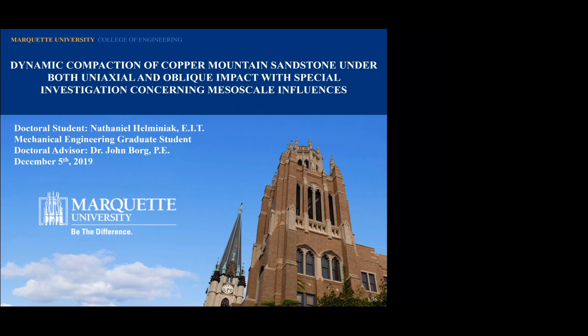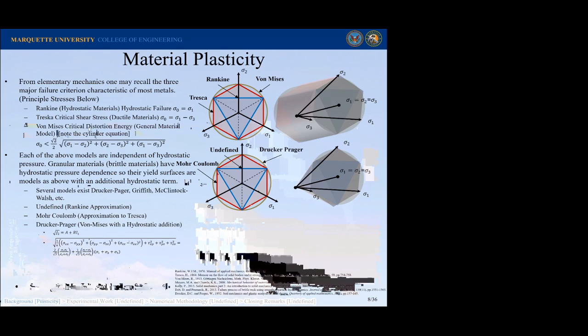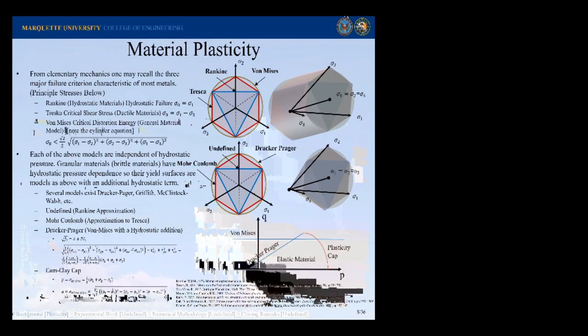Pretty awesome. So we start off with this Drucker-Prager model, which you can see right here, and it's just got this extra term inside here. So you've got your J2 stress, same as up here, and then you've just got some A plus BI. That's a linear line. That's the line of this cone right here. Pretty awesome. And if you want to get even fancier, you can put on this plasticity cap right over here. You can see these are all uncapped. This plasticity cap bridges the gap between pressure shear and then if you have yield under hydrostatic pressure.